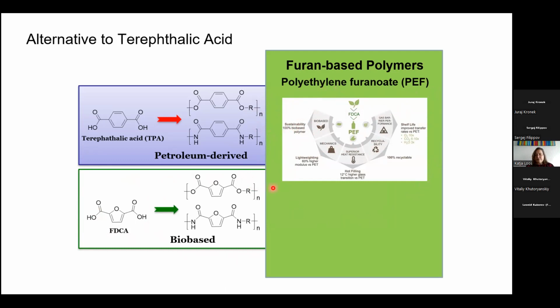And what they found out, but also others in the field, of course, is that the polymer has a bit higher thermal stability than PET. It's still not that you can really have coffee cups from PEF, but there are, of course, again, ways to do that. It's bio-based. Because it has higher gas barrier properties, you can make the plastic bottles thinner. And that's, of course, something which really plays into sustainability, because if your plastic bottle weighs less, then the 1,000 plastic bottles that get transported need less gas, so this is really good. It's 100% recyclable, but of course PET is also 100% recyclable. Yeah, the gas barrier properties are really better.